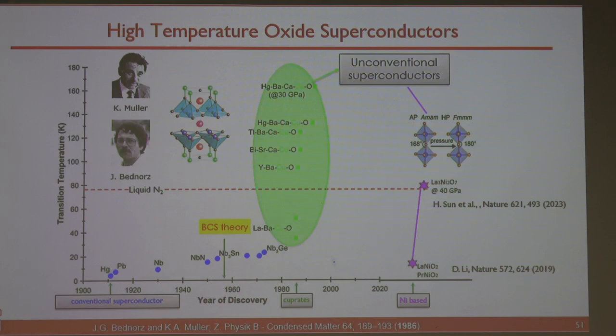What I'm mostly thinking about is the phonon channels, which need to be compatible with the D-wave superconductor. You don't want a large momentum transfer, because large momentum transfer means you're mixing positive and negative lobes of the wave function. That's bad. So far there's plenty of good evidence that there's a small Q.